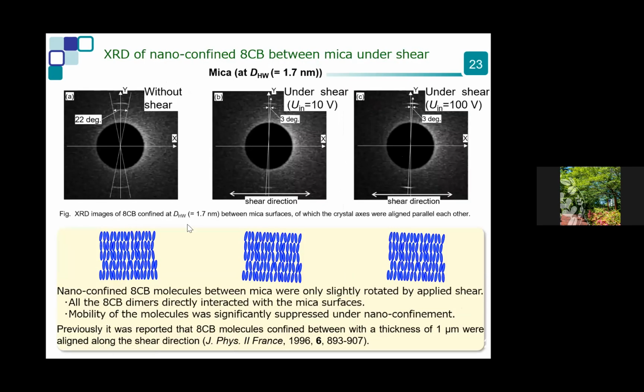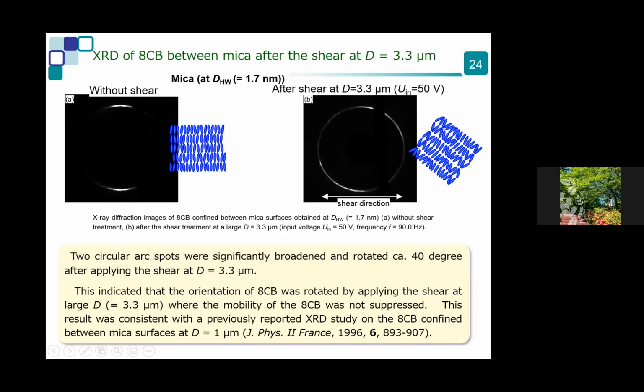If we shear such systems in the confined state, we only see a very small change in the diffraction spot, an angle change of 3 degrees. But if we shear at a very large gap, and then narrow the gap, we can observe the shear effect.